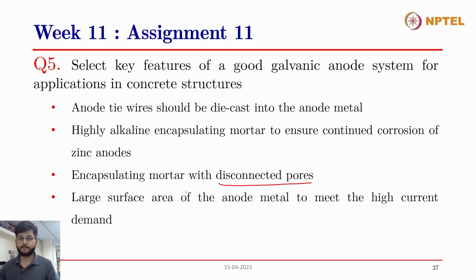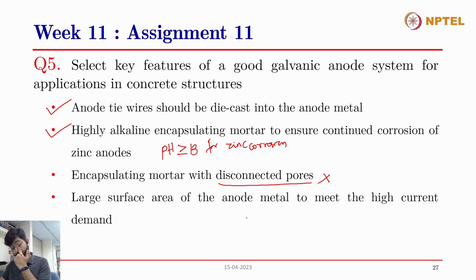Anode tie wires should be die cast. Yes, it was told in the lecture also. Highly alkaline encapsulating mortar to ensure continued corrosion. Yes, we require an alkaline environment with pH of the order of more than 13 or so for zinc, so that zinc keeps on corroding. Then disconnected pores are not desired, because these corrosion products will require some space. In case we have disconnected pores, those may not be sufficient to accommodate the voluminous products. Then a large surface area of the anode metal to meet the high current demand. Yes, that is also correct. So the third answer is not correct. Others are okay. Thank you, Dr. Satish. Yes, you have rightly answered actually.